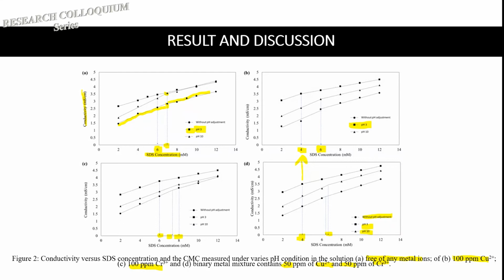It gives us a little hint that in a binary mixture that contains copper and chromium, copper is the one taking the initiative, the one which has preferential adsorption towards the SDS micelle. So it gives us a clue that in this system we can probably perform a selective separation, in which we expect that the Cu will eventually be easily adsorbed onto the SDS micelle, but the chromium is not interested in being bound onto this SDS micelle.